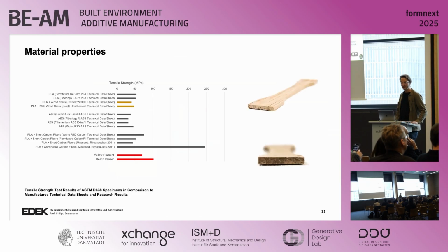And you can see here the material properties in comparison on the strength, and on the top you can actually see this kind of brown color. You can see that PLA actually even gets a little bit less strength if you add the wood fibers to it. So it doesn't add to the strength. And you can see also that these willows achieve a much better performance, comparable to PLA with carbon fibers. And then also these beech veneers, they're even a bit better.